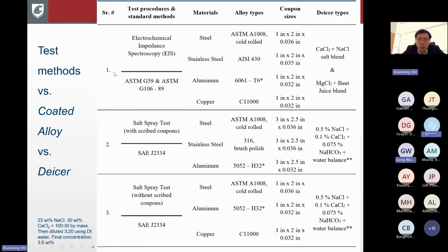For instance, in group 1 or series 1, we have used a non-destructive evaluation method called EIS, or electrochemical impedance spectroscopy, which gives a lot of mechanistic detail of how severe the corrosion is and why it's that way. And then the second series of tests is the salt spray test. Like I mentioned earlier, it corresponds to field performance really well. So that's fortunate.